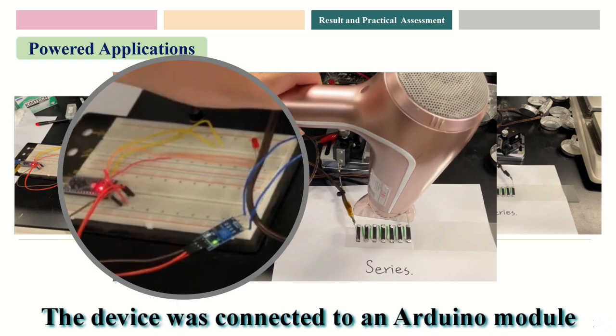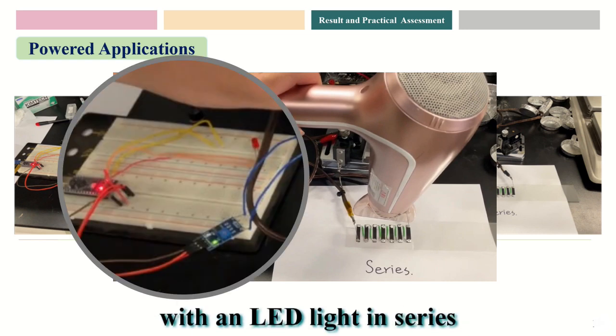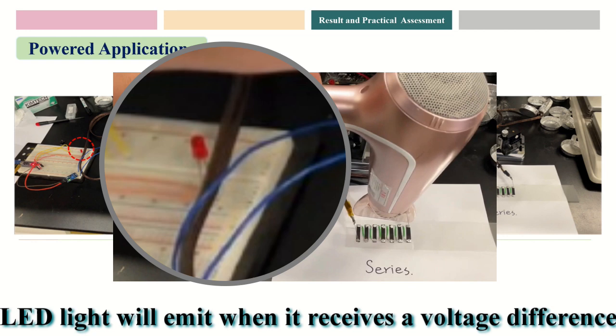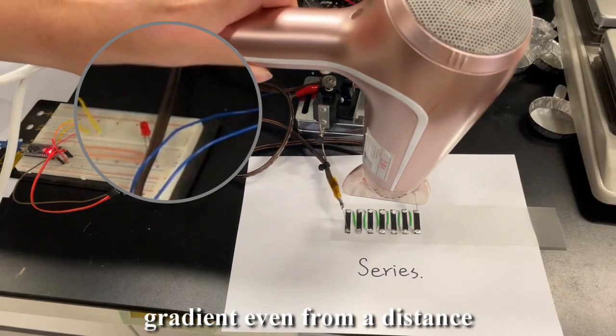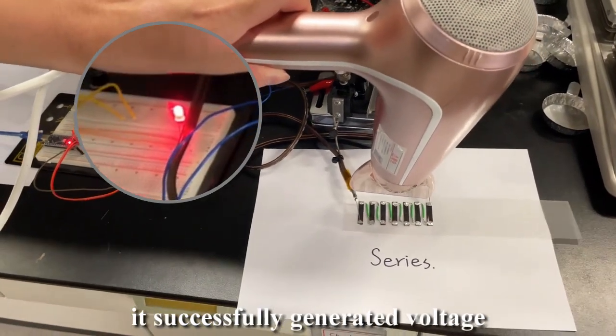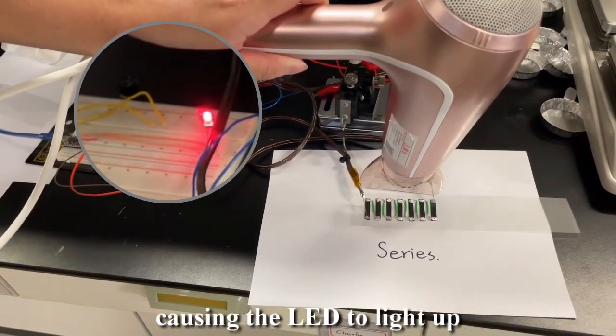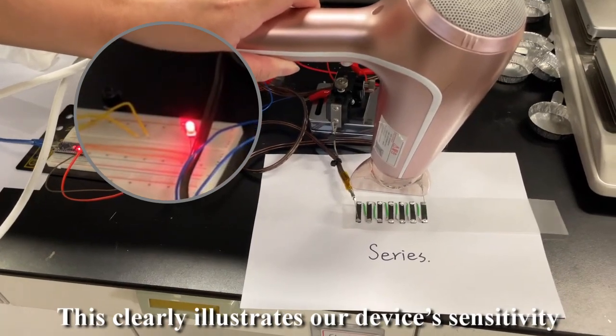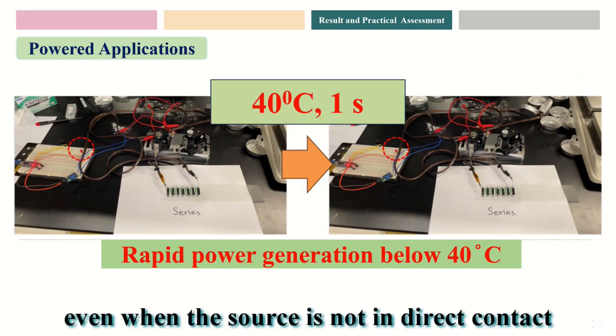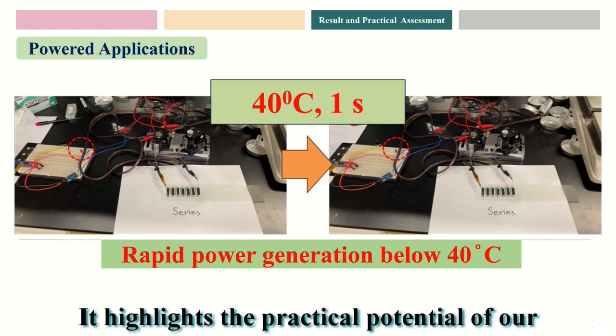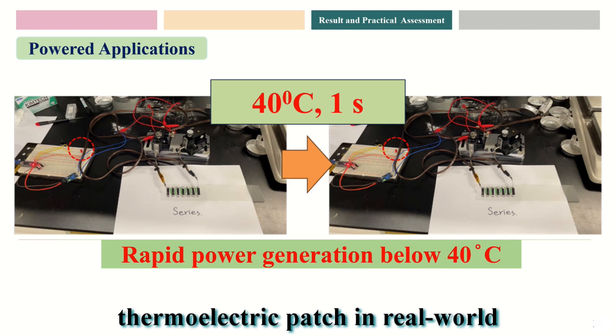The device was connected to an Arduino module with an LED light in series. The LED light will emit when it receives a voltage difference. As shown in the video, when the device detected a temperature gradient even from a distance, it successfully generated voltage, causing the LED to light up. This clearly illustrates our device's sensitivity and responsiveness to heat, even when the source is not in direct contact. It highlights the practical potential of our thermoelectric patch in real-world low-grade heat occasions.